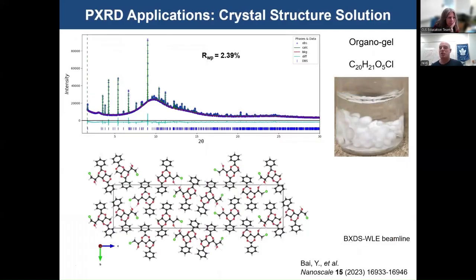So powder diffraction is good at looking at mixtures of crystalline materials, but you can look at pure materials too. Most crystal structures are solved using single crystal methods, like I showed you previously, but you can solve crystal structures with powders as well. And for many technological materials, large single crystals can't be synthesized. So powder diffraction can be critical because sometimes there's no other way to actually get to the crystal structure. This powder pattern was obtained from a new organogel material that could potentially be used for drug delivery or possibly even as a food additive.